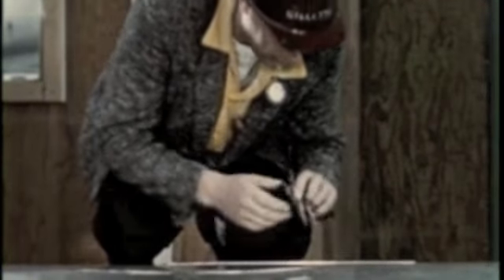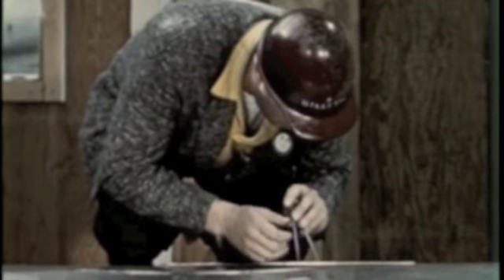Following each series of 50 pressure cycles, measurements are taken of the crack and compared with the length of the crack at the beginning of the test. Although the crack grew slightly, there was no indication of serious traveling of the rupture. The section depressurizes slowly without seriously weakening the structure.